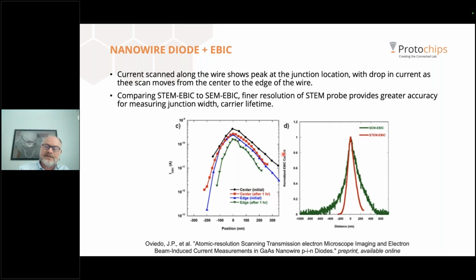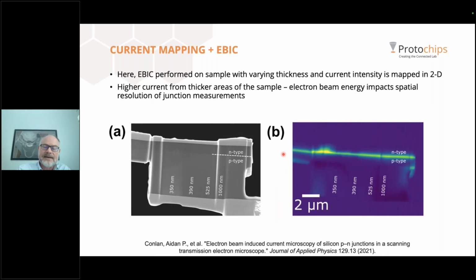Now, this can be extended to 2D by scanning across a sample. Here, different paper, the authors did EBIC on a FIB lamella that has varying thickness from left to right, and the current intensity is plotted on the right in 2D. So the PN junction there is easily visualized in the current intensity, and it can be imaged as a function of bias. As expected, you see higher current from the thick regions. The authors also found that the electron beam energy impacts the spatial resolution that you can have at the junction. And so lots of different electronic parameters can be extracted from data like that.